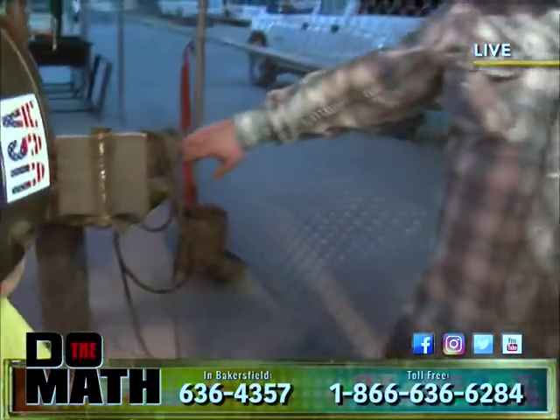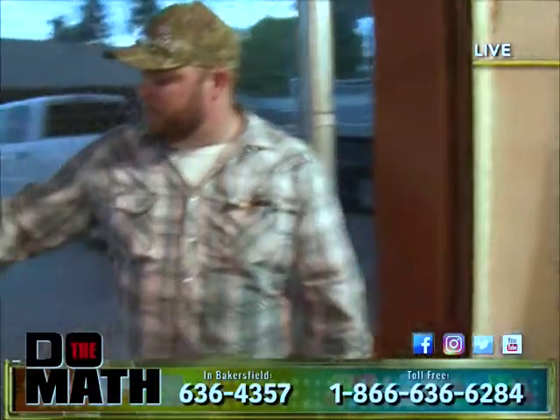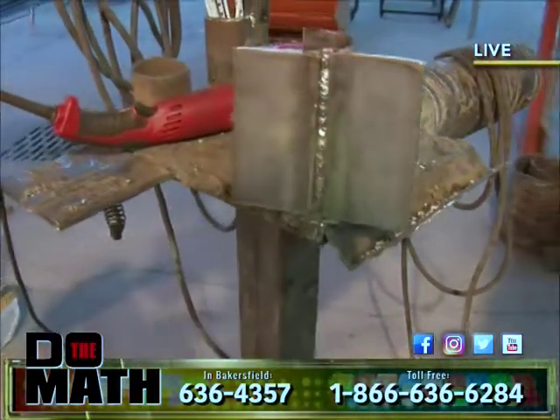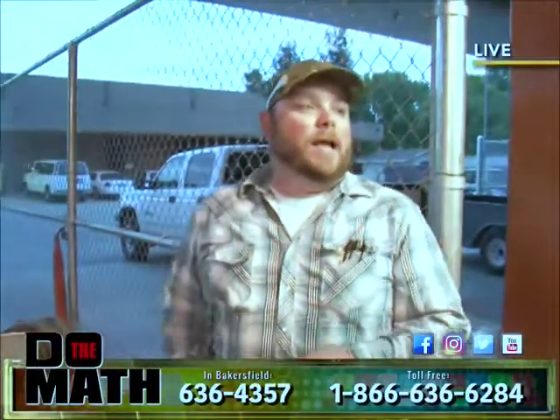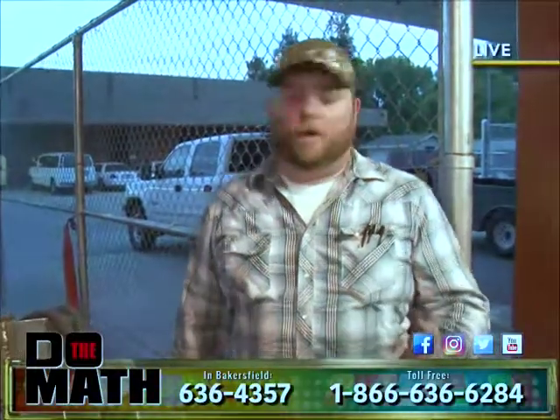22.5 degrees. But the American Welding Society, you get a variance of about a degree. So it's not extreme, but when you're looking at 22.5 degrees, that's pretty critical as far as the bevel. Now what that does, if there's not enough bevel in there, you'll have a hard time filling up the weld. If the bevel's too far open, you'll have to run a lot more weld passes, and the more weld passes, the bigger chance you have for impurities, slag inclusion, porosity.